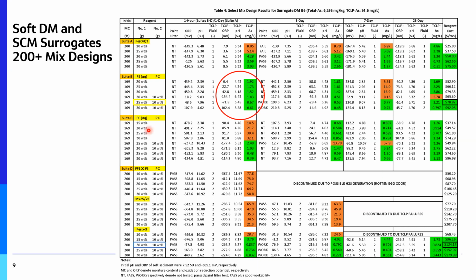Then we have our Portland cement. So let's take a look at what we got here. Remember, I said we needed to be on the pH between 4 and 8, right? So this ferric sulfate combination with and without Portland cement did very well, keeping us in that sweet spot on pH. And as a result, even after 1 hour of reaction, our T-clips were well below 5. The question was, was that going to last out to 28 days continuously? So we had a number of these fail, right? The ferric sulfate only. Part of the reason for that is we drifted out of the pH optimal range.